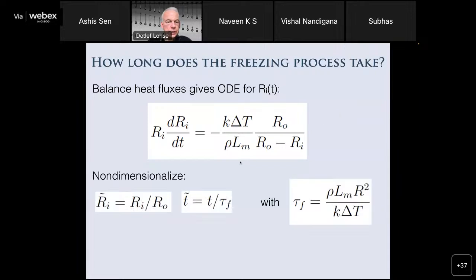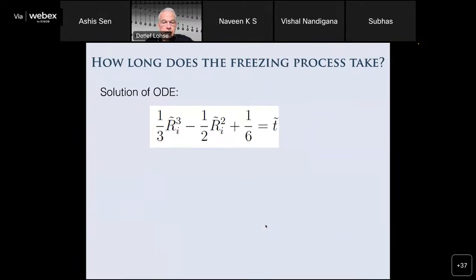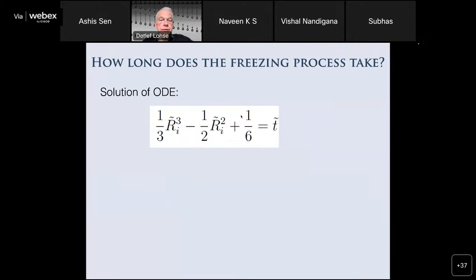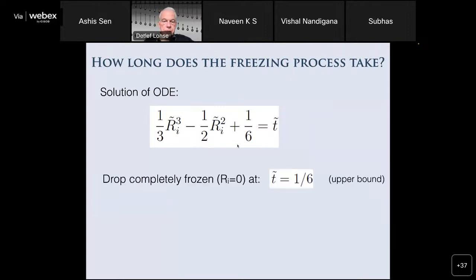And when you now non-dimensionalize this in this proper way with this proper time scale, which is given by the latent heat and by the temperature difference, and of course, in particular by the size of the droplet, then you get this very, very easy differential equation. And when you rewrite it, you in fact can solve this analytically. So this ODE here, remarkably, is easy enough that you can solve analytically. So this is the analytical solution of this ODE.